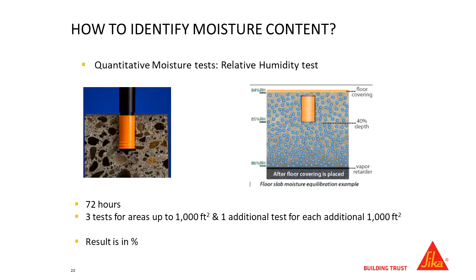The more highly accepted in the industry method of testing moisture has turned to the relative humidity test. The reason for that is that you can get a snapshot, but you can get it constantly over a long range of time. You drill down into the slab, you place your probe down in there that measures the relative humidity, and then you can get a reading with either a sort of a pen that you can stick down to a probe. There's probes now that you can get readings on your phone if you're close by. The nice thing about the probes is you can skim over top of it, you can finish your flooring, and if there's ever a reason or an issue, you can go back there and you can continue to get results off of that probe that's embedded in the slab.